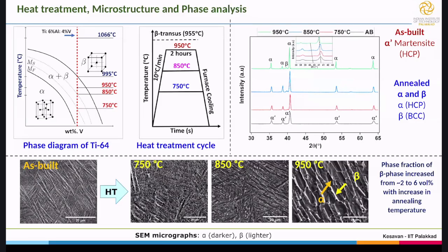Particularly, the phase fraction of the beta increases from 2 to 6 volume percent with increasing annealing temperature. It is 2% for the 750 degrees Celsius annealing temperature, and 6 volume percent for 950. You can see this in the XRD plot as well. As we increase the temperature, alpha and beta separate out, and they are distinct.